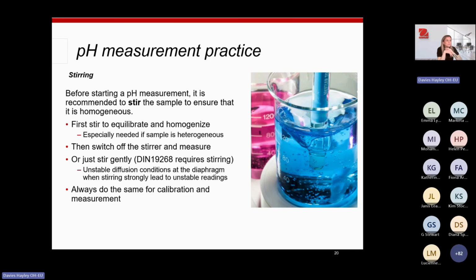Good measurement practice when you're taking the sample is making sure that the sample is the right consistency. So it's always important before you do your pH testing to stir the sample to make sure that it's all homogenized. Then once you've stirred the sample and it's all homogenized and mixed up, you can switch off the stirrer and then you can measure.